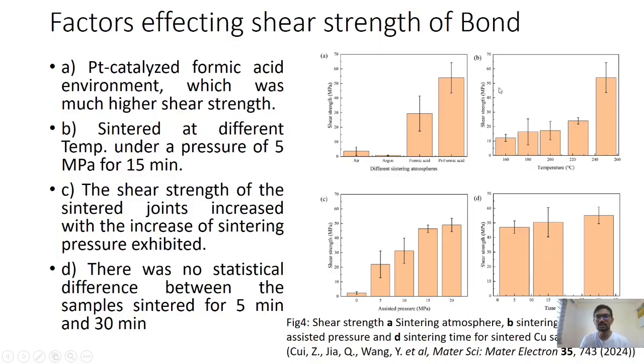The second parameter is temperature. As you can see in figure 4 part B, as we increase the temperature, the shear strength increases. At 160 degrees we get shear strength of about 12 megapascal, and at 220 degrees we get about 25 megapascal. Beyond 240 degrees the shear strength increases very fast, to about 55 megapascal. Why does the shear strength increase so fast? Because the sintering kinetics increases after 240 degrees, due to which the cohesiveness between copper nanoparticles increases, and the adhesion between copper and the copper substrate also increases.